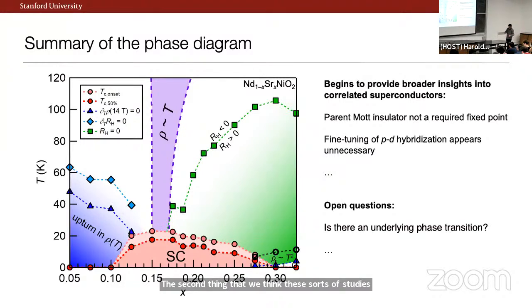The second thing that we think these sorts of studies are helping us understand is that you and I and this person may have different ideas of what's driving superconductivity in the copper oxide systems. Now we have a very interesting situation where we can test some of these ideas and make a comparative statement. So two of the ones that we think we can say, again, maybe too much jargon here, is that the Mott insulator, that correlated antiferromagnetic insulating parent compound, does not appear to be a required fixed point or starting point for this phenomenology. We never have that. The second question would be the details of these orbital levels I was telling you about. Those fine details don't seem to be relevant for the basic appearance of superconductivity in this form.